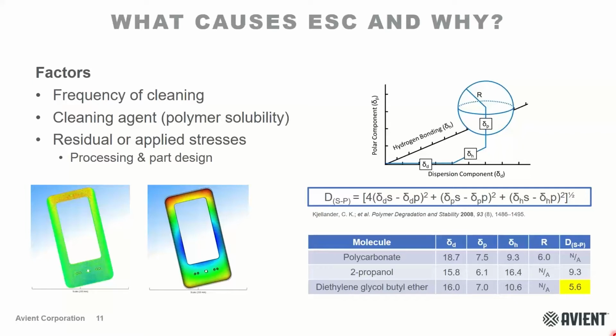A lot of that comes down to the polymer solubility and its interaction with the cleaning agent or the chemical that it's being exposed to. On the figure on the right, what you're looking at here is a polymer solubility sphere. It's a three-dimensional plot that's defined by the Hansen solubility parameters. All organic compounds can be described by their intermolecular forces. They can have polar-polar interactions, dispersive interactions, as well as hydrogen bonding. The culmination of those interactions for a polymeric material will define what's called the polymer solubility sphere. And this sphere has a radius associated with it.